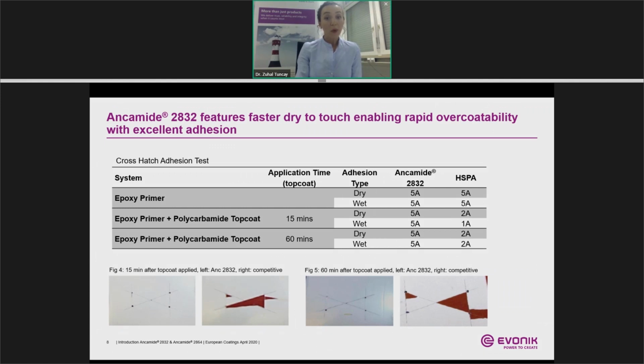In the second set, a polycarbamide topcoat is applied after the epoxy primer has cured for 15 minutes. And the third set, where the epoxy primer has been cured for 60 minutes before the top coat is applied. As you see, crosshatch adhesion for 2832 results in 5A, which is the highest rating. By comparison, with the competitive system a significant level of delamination is observed, resulting in crosshatch adhesion in a range of 1A to 2A. In figures 4 and 5, you see on the pictures our observations.